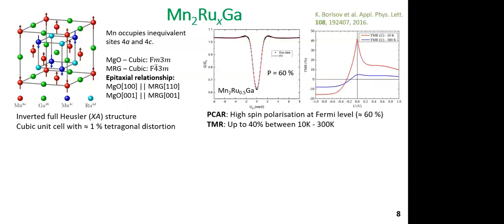The spin polarization measured by PCAR is about 60%. This is far from the ideal 100%, but even in the cobalt-based half metals that I have shown you in the previous slide, the spin polarization is not too far from 60%. I think it could be up to 70 or 80%.